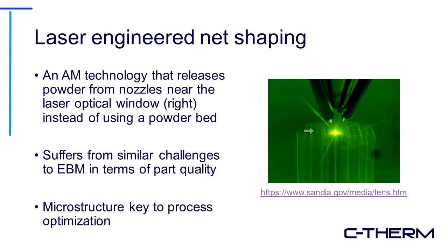Instead of the way that most additive manufacturing technologies deal with adding the different layers, most of them use a bed of powder. In this technology, the powder is being supplied by these tubes here. So they apply the powder basically where it's needed, and that gives them a tighter control over where the powder is added. The other benefit is that you don't need a huge bed of powder, so you don't wind up wasting as much of the powder material, which is quite attractive if you have an expensive starting material, for example.